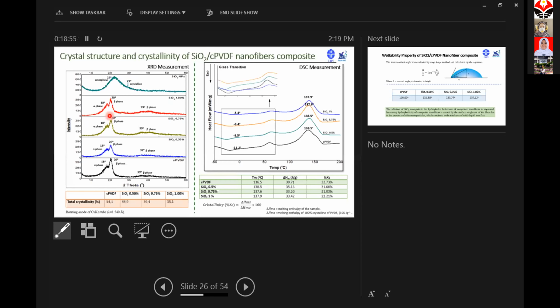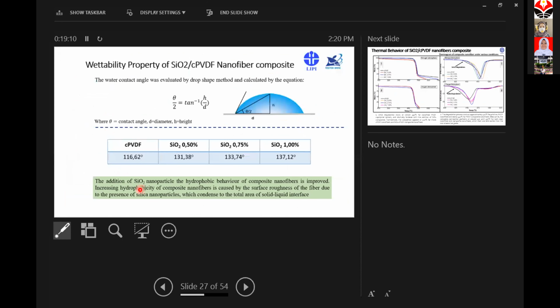Okay, what is the effect of the nanoparticle on the crystallinity? You can see here, increase of the silica content decreases the crystallinity of the polymer. And then we try to see the effect of silica on the wettability of the separator. You can see here, increase of silica increases the water contact angle. It means the nanofiber becomes more hydrophobic than pristine co-PVDF.